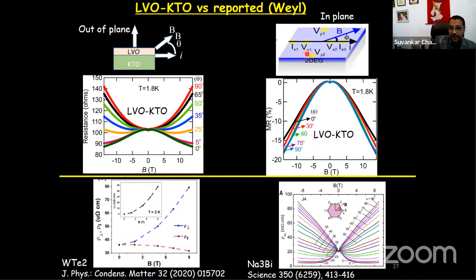But in the case of in-plane geometry, so this is the in-plane measurement. So we are applying now the field in the plane containing the 2DEG, that is the XY plane, making an angle phi with the current. So phi equals 0, and now in this case theta is of course 0 always. So phi equals 0 for our material, you see negative magnetoresistance. Even for phi equals 90, you see negative magnetoresistance, which has a sharp contrast to what people have seen in Weyl material. If you change the angle phi in the case of Weyl material, in plane also you should see a negative to positive magnetoresistance transformation.